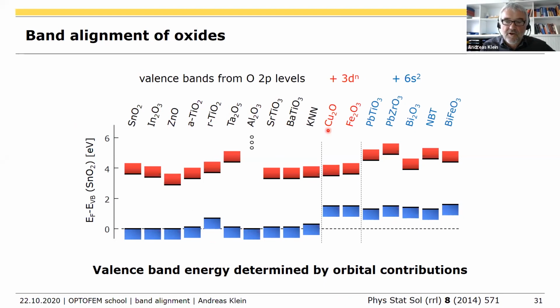And then there is copper oxide with the 3d orbitals, also iron oxide, which has a partially filled 3d shell. So again, you have here not only oxygen 2p, but oxygen 2p and iron 3d. Surprisingly, also lead titanate and lead zirconate, and even bismuth oxide, sodium bismuth titanate. Bismuth ferrite is a different case because it contains bismuth and iron. But all these materials which contain occupied 6s states also show higher valence band maxima.